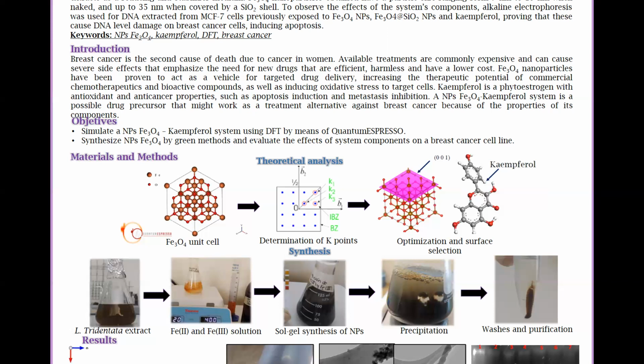the BFGS method. For the experimental part, we used Larrea tridentata dry leaves to make an aqueous extract in a 1:10 ratio. We then made an iron 2 and iron 3 solution in a 1:1 molar ratio, to which we added previously prepared aqueous extract in a 2:3 ratio. Iron salts would act as a precursor for the nanoparticles, while the extract provided a reducing and stabilizer environment in which the needed reaction would take place.